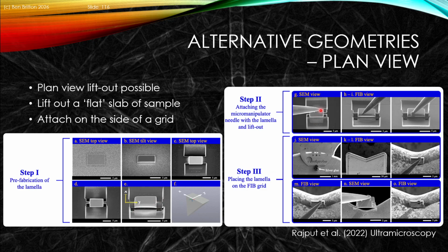You attach it to your needle, and then you could use, for instance, the manipulator to then bring it, and here we've put the grid, the Omniprobe grid, now on the side of a stub. So then we can effectively side weld that grid on the side of the stub, and then we can effectively polish to remove the material and get it to be super thin to enable us to have a plan view rather than cross-section of our object in there.